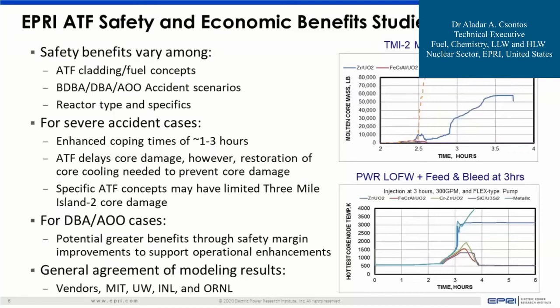For design-basis accidents, in this AOO in particular, this is a PWR loss of feedwater and feed and bleed case, where we have 300 GPM of water being injected 3 hours after the accident scenario. And in this case, what you see here is that the three ATF concepts, the Zirc, coated Zirc, the FeCrAl, and silicon carbide, all turn the decay heat curves over so that you could prevent a core damage event here. And so you can see here that these concepts do have an accident tolerance feature that can provide increased margins, and that's a big part of how we then look into the operational enhancements that come about from those safety margin improvements.